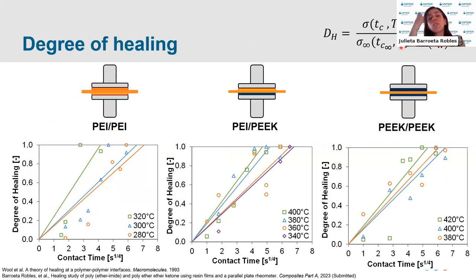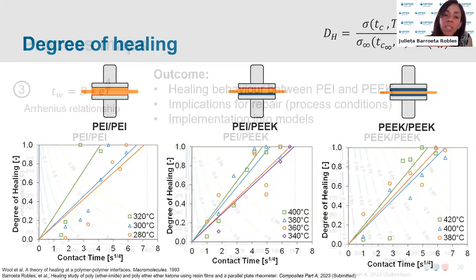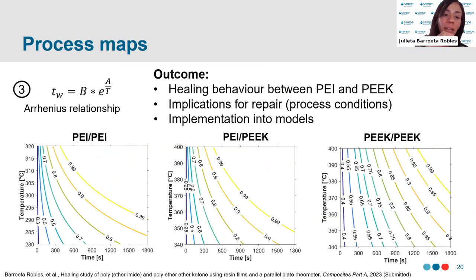Now, something that we know from thermoplastic welding, thermoplastic processing, is that when we use higher temperatures, then we need less time in order to attain a high consolidation. So with this relationship, that means that we can use Arrhenius. And with this relationship, then, we were able to generate these process maps for each of the material combinations. So now we can have a better understanding of what's happening and the healing behavior between these materials. So what would be the implications for repair then?